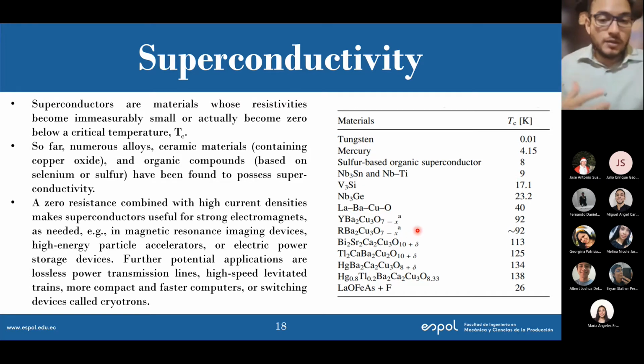And obviously they started to synthesize these. And why? What was the motivation? Because the temperature is a lot higher. Well, not a lot higher, but at least it's not really close to the absolute zero. Yes, it's still cold, quite low, 92 Kelvin, 100 Kelvin, but it's not as low as 4 Kelvin, 0 Kelvin. That's extremely low, right? So that's why there is interest in synthesizing this type of superconductors, the ceramic superconductors, because they have a higher critical temperature. Now, if we think of superconductivity, we know that it is quite useful, right?